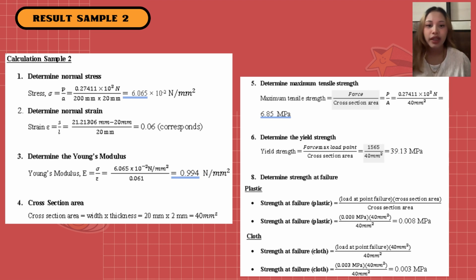Maximum tensile strength, which is 6.85 MPa, and yield strength 39.13. The last one is strength at failure for plastic and cloth, same like sample number 1, which is 0.008 MPa for plastic, and then 0.003 MPa for cloth.